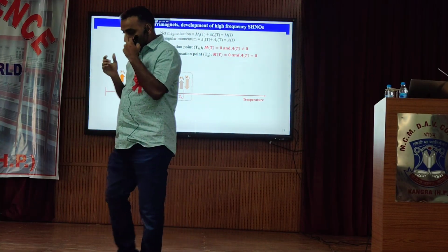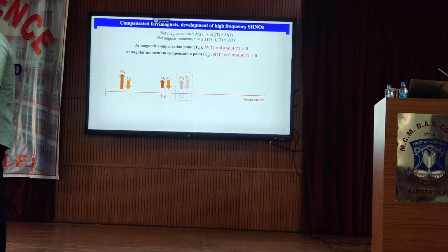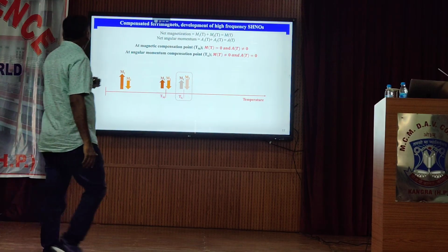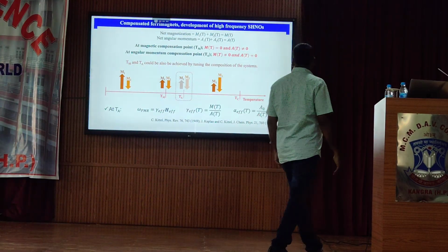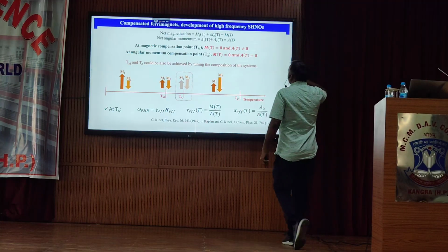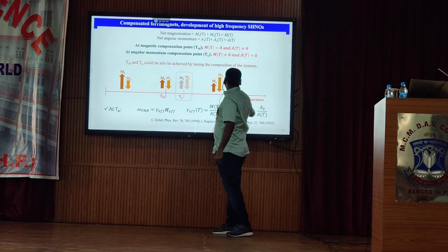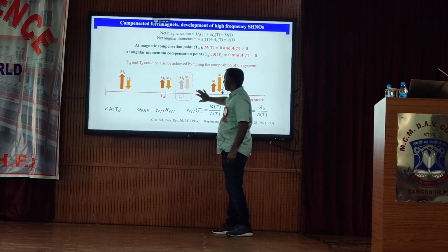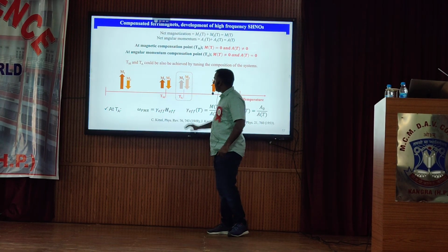If we make an alloy, like cobalt gadolinium, and tune the composition, we can get a composition whose angular compensation point is near room temperature. Then we can work at room temperature, and what we look for in a device is materials that can work at room temperature. So there are two ways, either changing the temperature or changing the composition of the system, to arrive at this point. We are interested in this point.